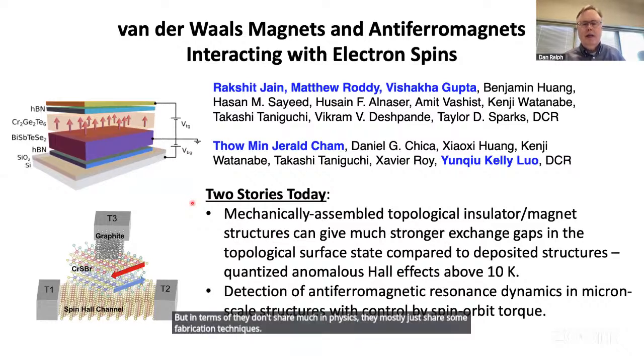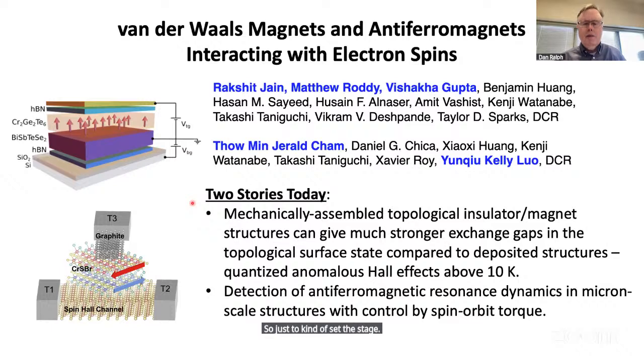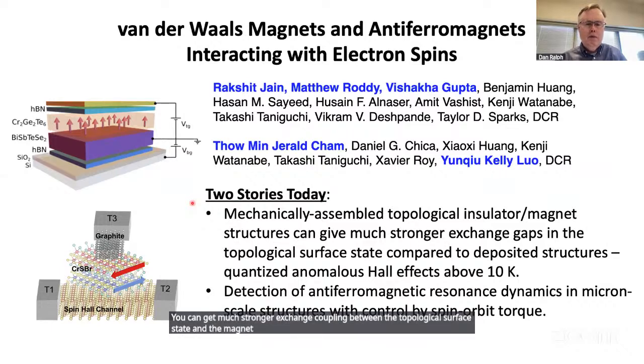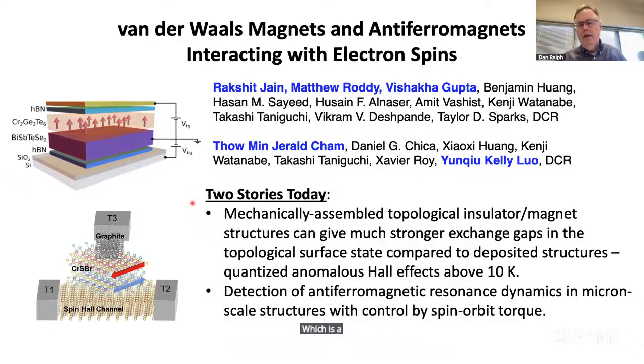So just to set the stage, the first project I'll talk about is what happens when you couple a topological insulator to a magnet. And what we found is if you do this using exfoliation and mechanical stacking, you can get much stronger exchange coupling between the topological surface state and the magnet compared to what's been seen before with MBE-grown structures. We see at least half-quantized anomalous Hall effects in the parity anomaly regime above 10 Kelvin, which is a factor of 100 higher temperature scale than what's been seen with MBE structures.